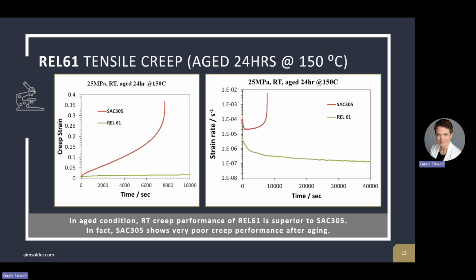This is a test where we looked at tensile creep when we aged the solders for 24 hours at 150 Celsius. We see that SAC305 experienced quite a bit of increase in creep strain, whereas REL61 did not. So the creep performance of REL61 was shown to be superior to SAC305 in this test.